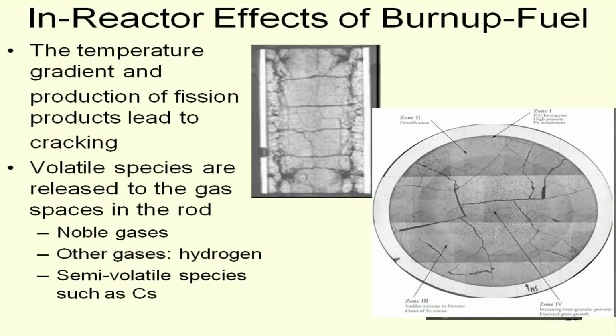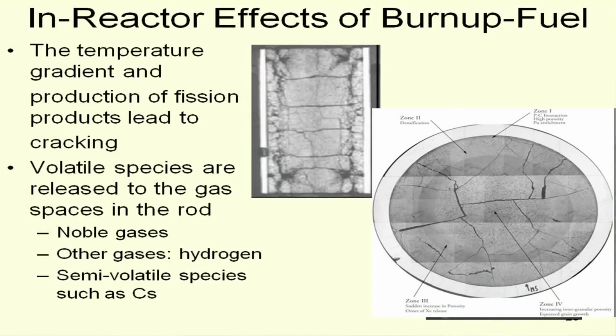The heating also leads to cracking, and you see this is an axial cross section and a radial cross section, and you see these cracks, which allow some volatile species to be released to the gas spaces in the rod, and maybe a little bit of hydrogen, and some of the semi-volatiles like cesium, and because of the chemistry, molybdenum can be a little bit volatile. Now that was sort of fuel pellet.